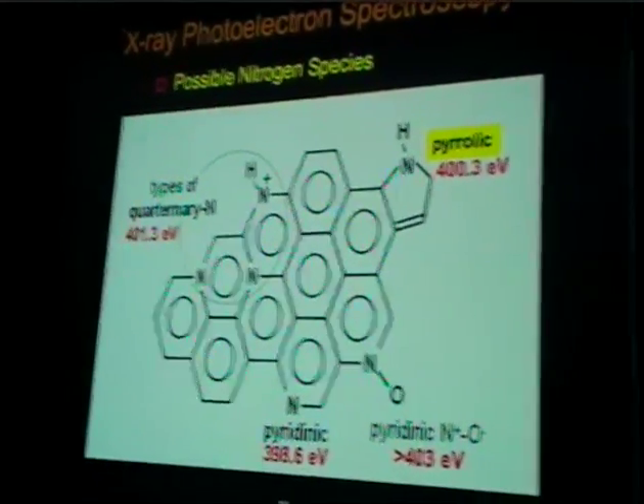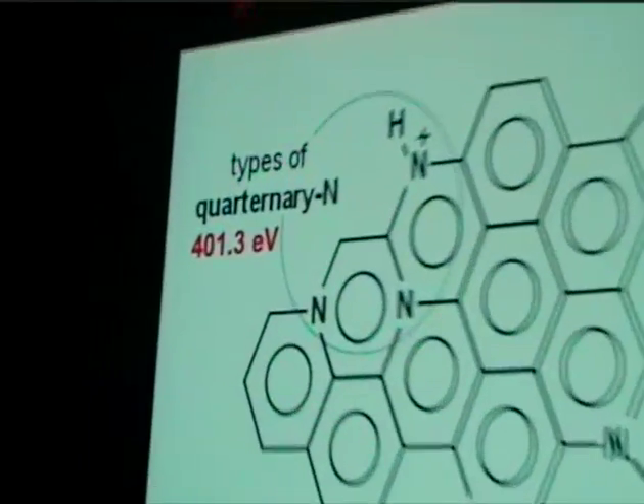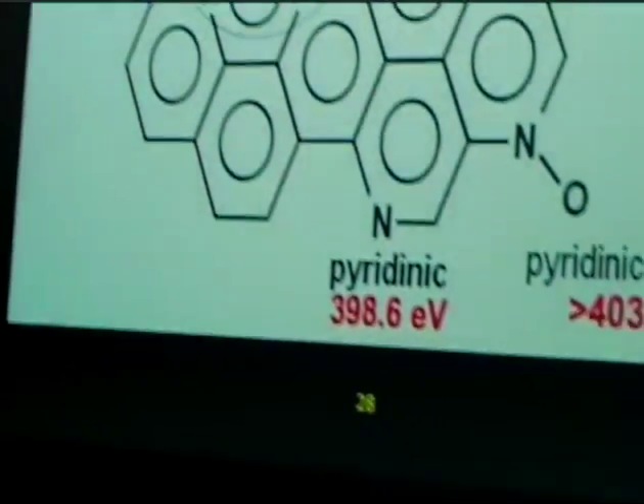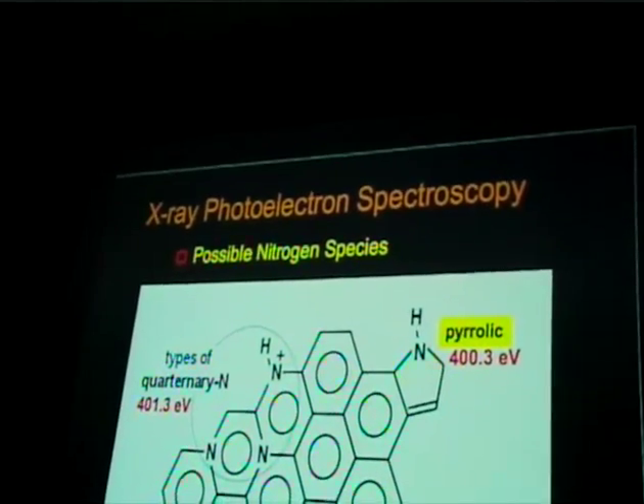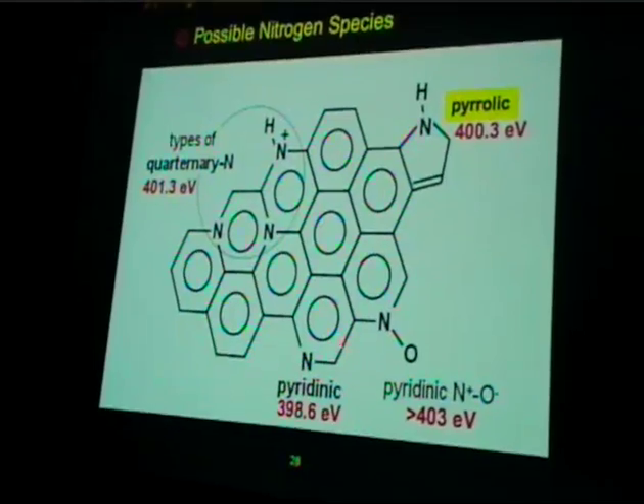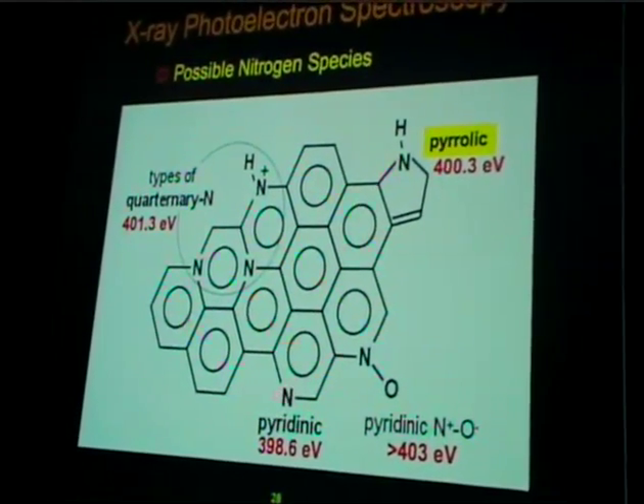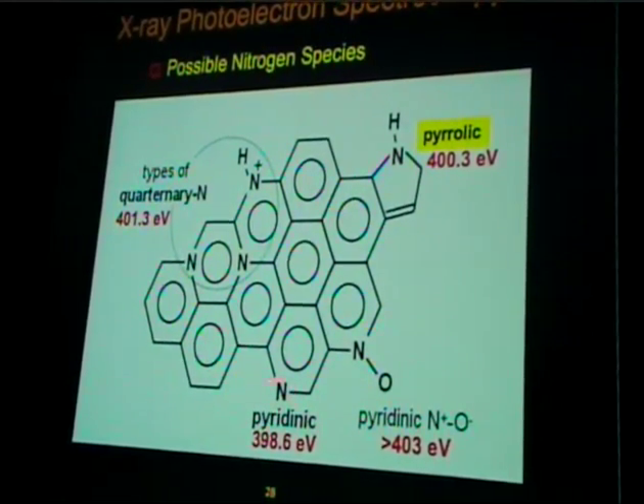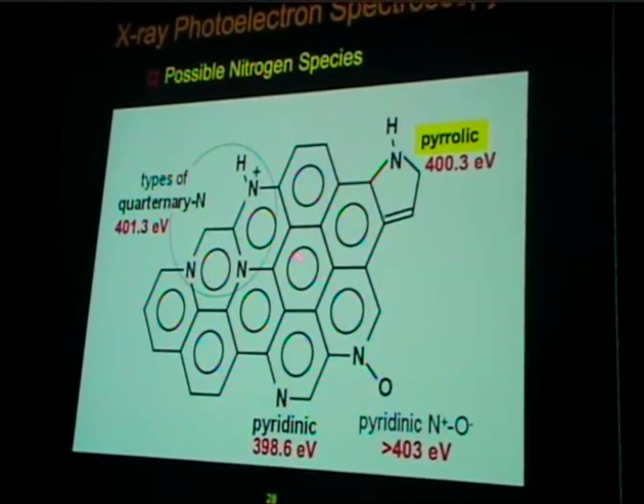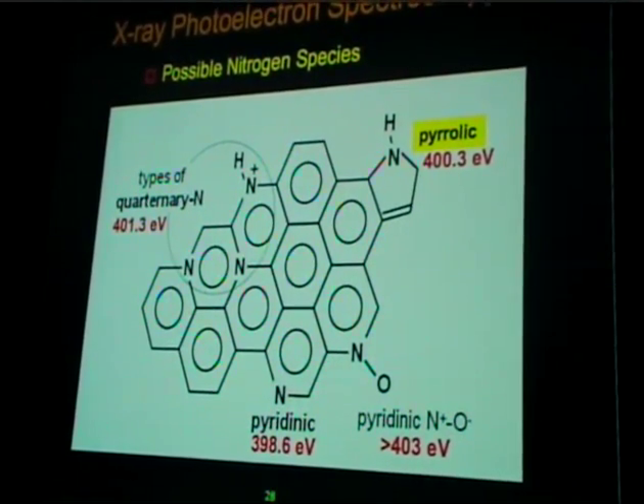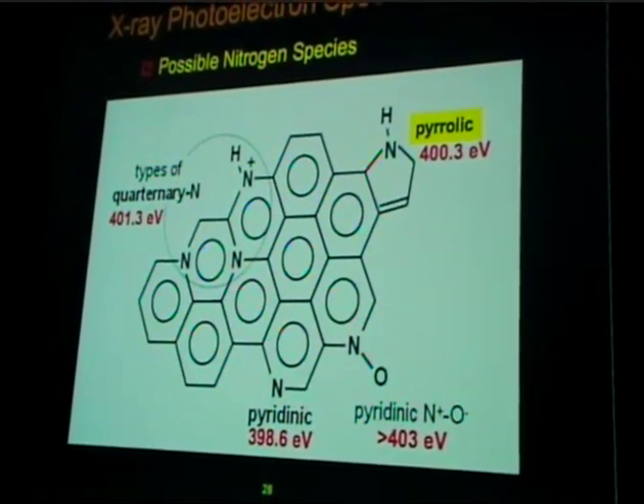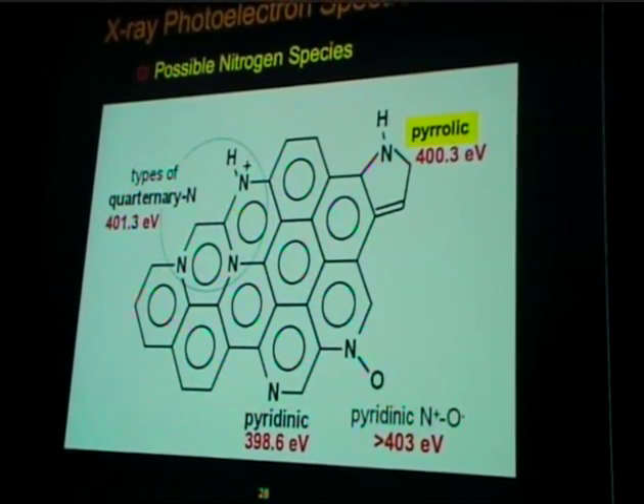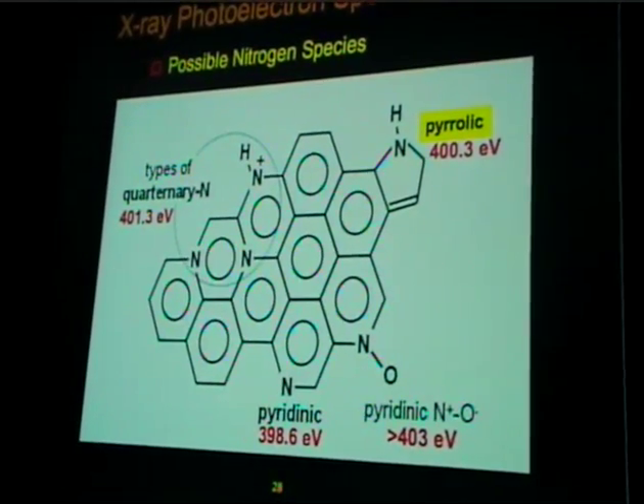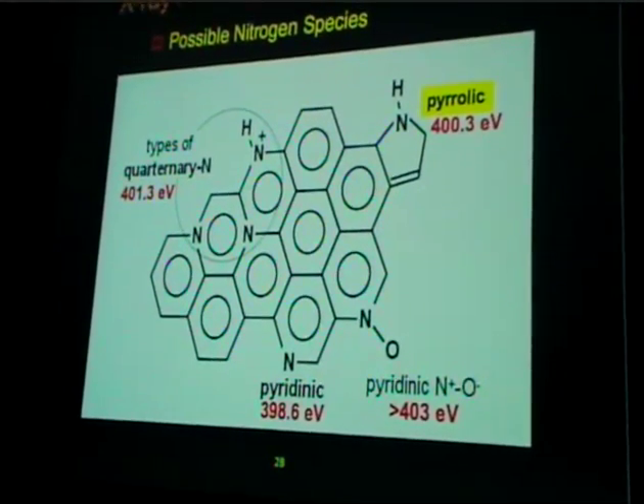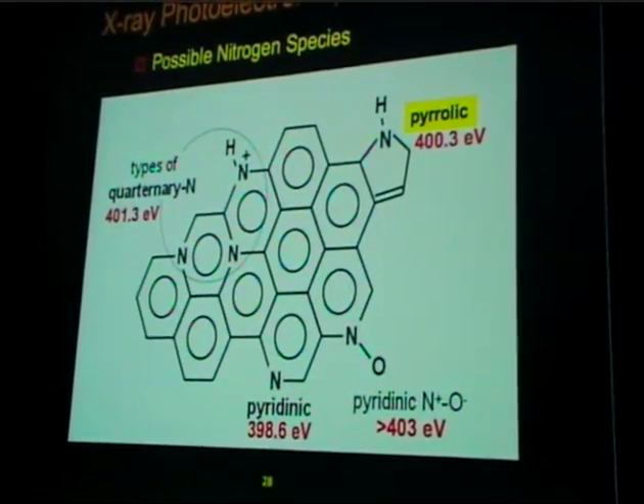Now, again, X-ray photoelectron spectroscopy is able to differentiate between different nitrogen species that can be formed over these graphite materials. For example, we could have pyridinic nitrogen, which can only take place at the edge sites, or we can have quaternary nitrogen, which can only be seen on the basal plane of the graphite. And these different nitrogen species can be differentiated through XPS because they give binding energies different enough.